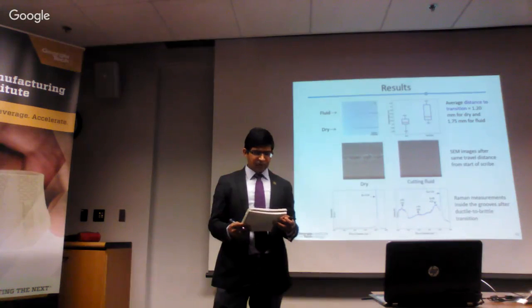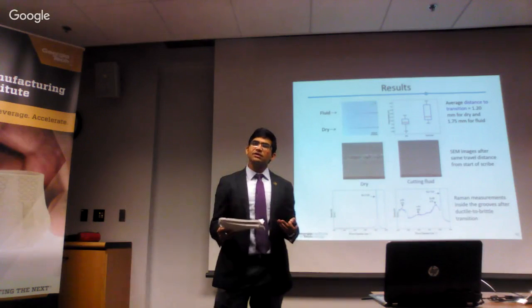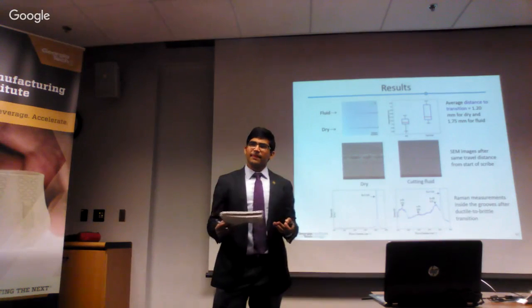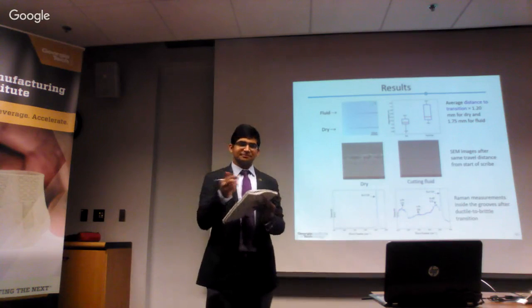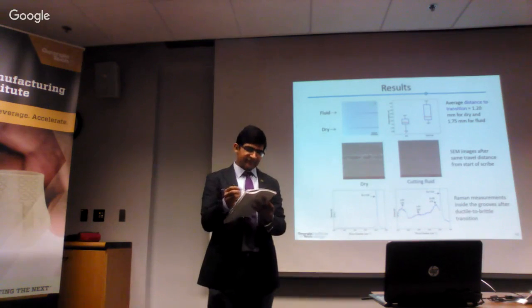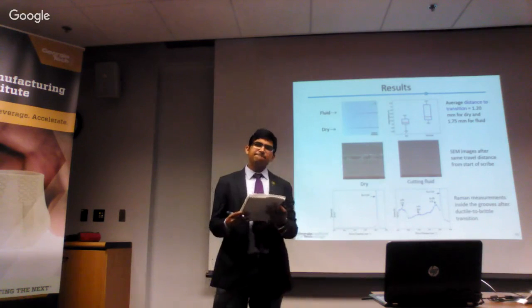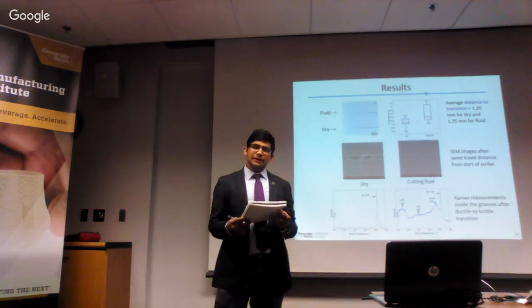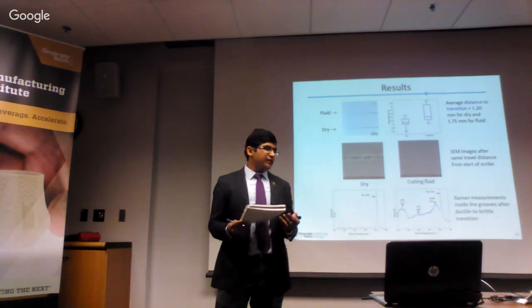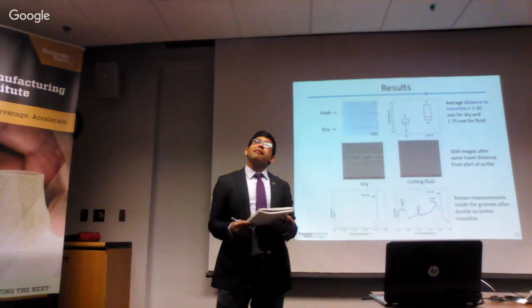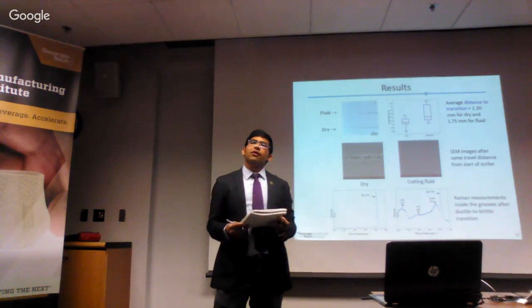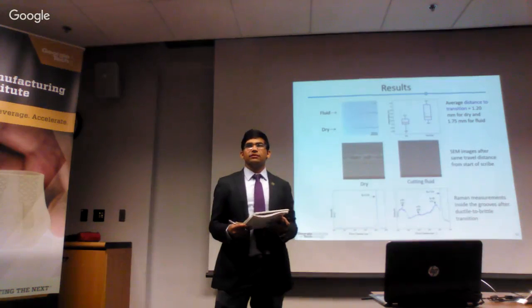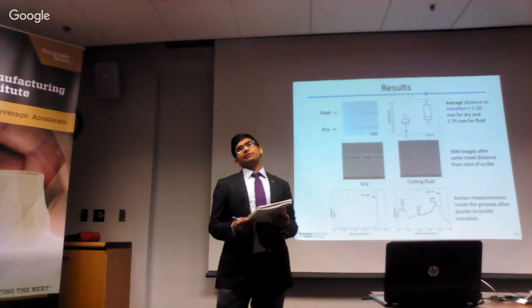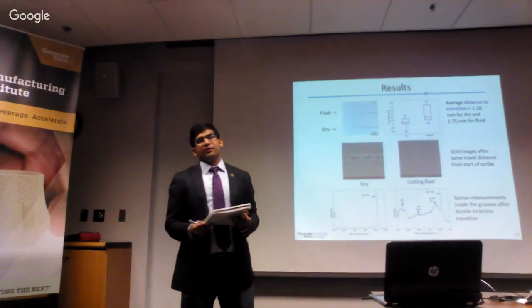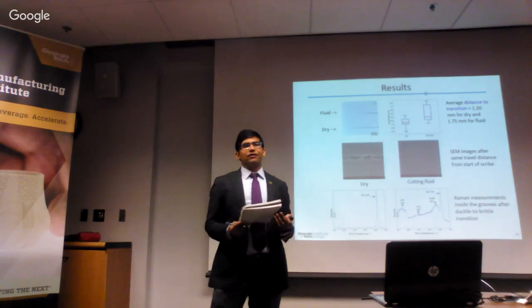Then about changing stresses with the liquid. Well, with the fluid, is it supporting some hydrostatic pressure? So you get a distribution of the pressure versus the dry. You might not get such a distribution. I'm just looking at that possibility, if it's changing, in other words, the effective profile or the effective stress state. That's what's on the slide, which would affect the stress state.